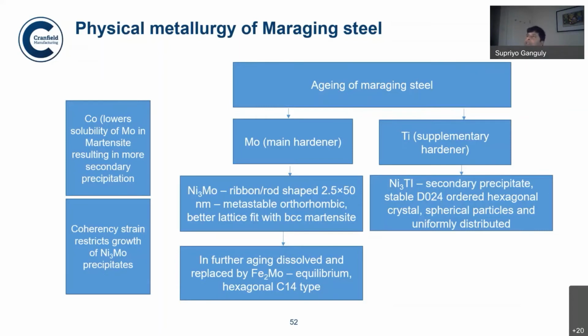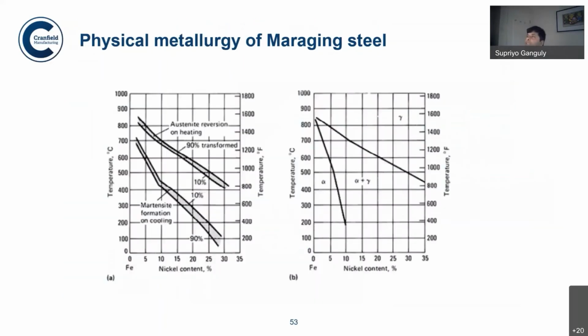These are the few physical metallurgy bits that are important, and also what is in this particular composition. So the heat treatment will depend on this. This is the metastable type of situation which we normally face, rather than the right hand side, which is the equilibrium. So there is a slight hysteresis between the austenite reversion and the austenite to martensite formation, basically, and that is important for heat treatment of this alloy.